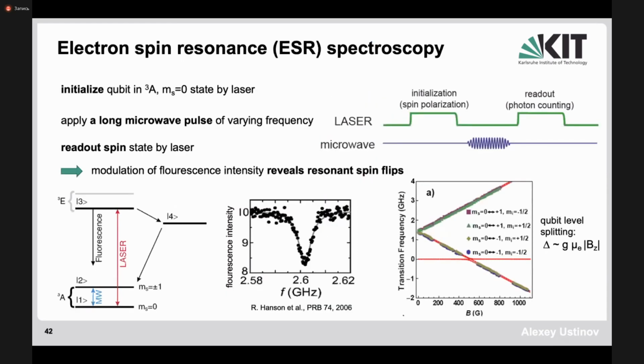Now, back to quantum computing, one, of course, can use the spin resonance technique to manipulate the spins. One can name the states with zero spin and non-zero spin as the two states you want to manipulate. And this is what is usually done in electron paramagnetic resonance or electron spin resonance. So one can initialize the system by laser, then observe the occupation of the state by fluorescence. And if you apply microwave, and then you have this resonant laser being your kind of measurement tool, then when you're occupying state 2, there will be no fluorescence, and if you occupy state 1, there will be fluorescence.